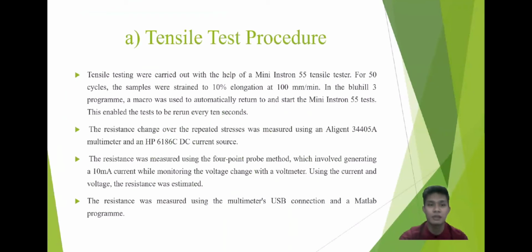Tensile testing was carried out with the help of a mini Instron 55 tensile tester. For 50 cycles, the samples were strained to 10% elongation at 100 mm per minute. In the Blue Hill 3 program, a macro was used to automatically return to and start the mini Instron 55 test. This enabled the test to be rerun every 10 seconds.